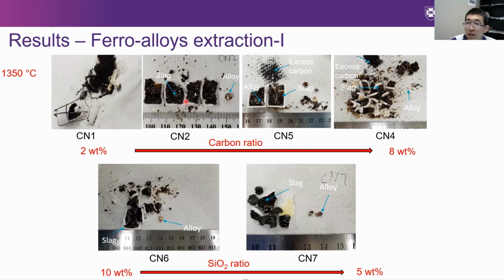So this is an indicator that we can optimize the slag at a low temperature and also achieve a full molten state. And then by changing the silica ratio from 10% to 5%, the slag is also glass.